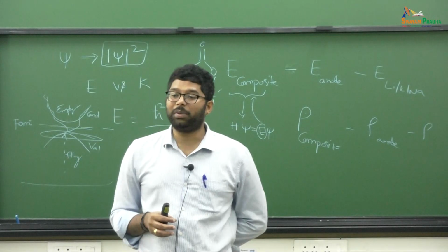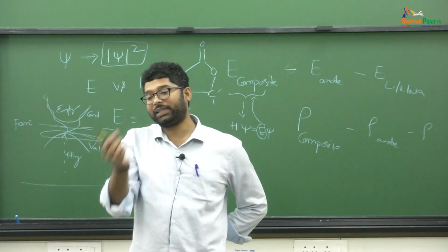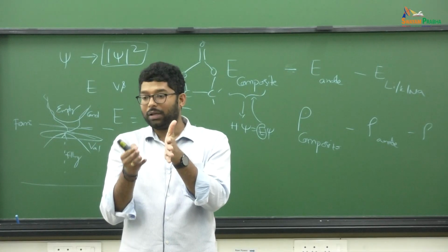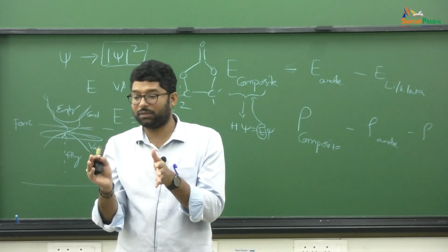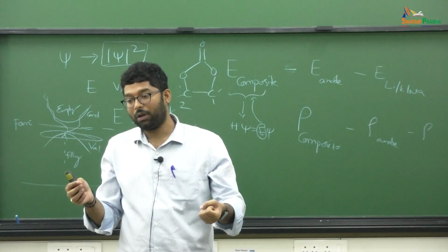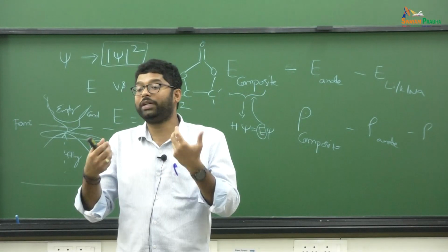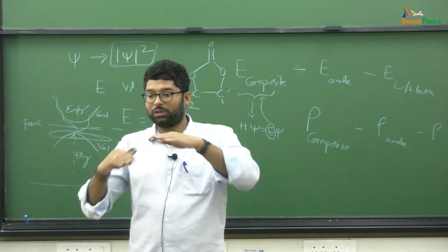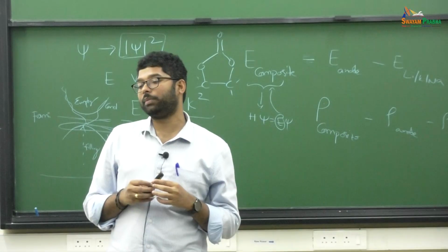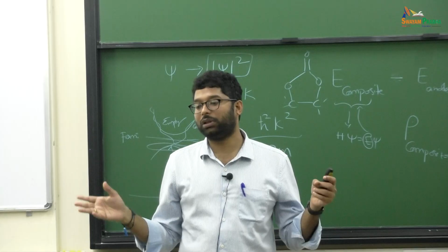No, so this is about the stability of the electrolyte. When you are considering the electrolyte, when you transfer the electrons to this, the electrolyte that is close to this electrode can also be reduced or oxidized. The electrons can go to this electrolyte and they can break it. What you want is something more stable, which will not be immediately reduced or immediately oxidized. So between these electrodes, the reduction and oxidation level should be maintained for this particular electrolyte. That's how generally you would be choosing. An electrolyte should be stable with the reduction and oxidation potentials of both the electrodes.